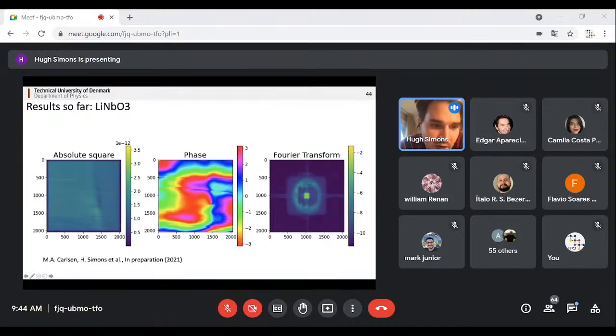So these are some measurements we've made of lithium niobate, which is a classic optical ferroelectric. The domains should in principle be invisible from diffraction, but we can get some contrast from the phase jump at the domain boundaries, which are here, and then we can quantify what this phase difference should be. Right now we're working on correlating this quantification of the phase to the polarization of the material. To do this, it turns out to be not so trivial, and we're building a multiscale model using DFT to try and calculate the correlation between optical phase and atomic displacement. So I'm hoping this should be at least finished in the next few months.